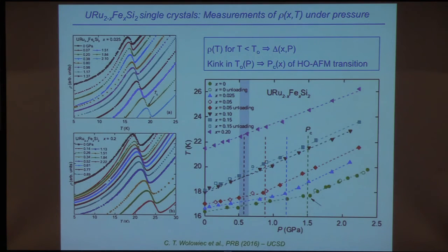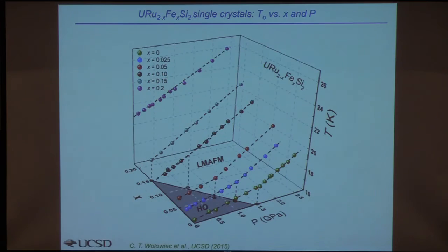All right, and so we wondered about this equivalence between pressure and iron concentration, and so we thought, well, we can do some studies under pressure. If the iron concentration was equivalent to adding a chemical pressure, then as we increase the iron concentration, the pressure at which the transition occurs should decrease, as determined from the kink in this phase boundary. And so for the pure compound, here's the kink at 1.5 GPa or 15 kilobars. And then as we add iron, you can see that this kink shifts to lower and lower pressures, okay? And then eventually there is no kink when it becomes purely antiferromagnetic.